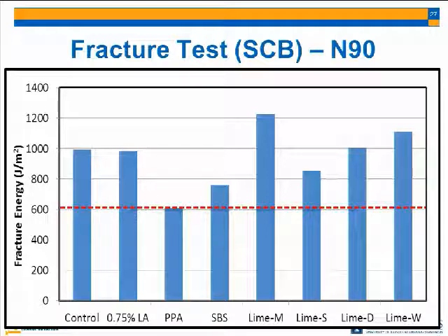When it breaks, it breaks outside. Even if it breaks inside, that's a very tiny amount, 1 or 0.5% of the binder, which is 5% of your whole mix. When I was talking before, the 1% moisture was of the aggregate, so there's no comparison.